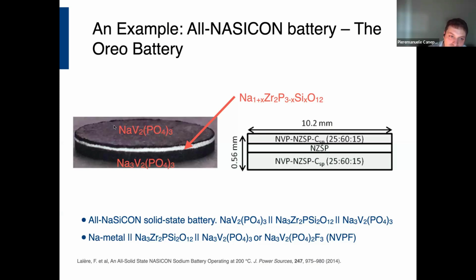So in here, in forming these electrodes, positive and negative electrodes, we use two different states of charge of sodium vanadium phosphate, which is a Nasicon by all means. The white part, so the cream in the Oreo biscuits, is sodium zirconium silicon phosphate, which is the first material, the Nasicon, that was discovered many, many years ago by John Goodenough.